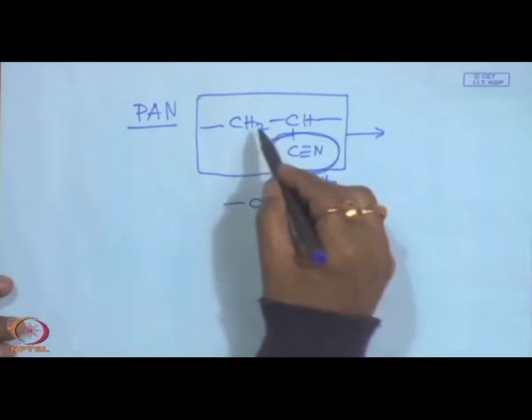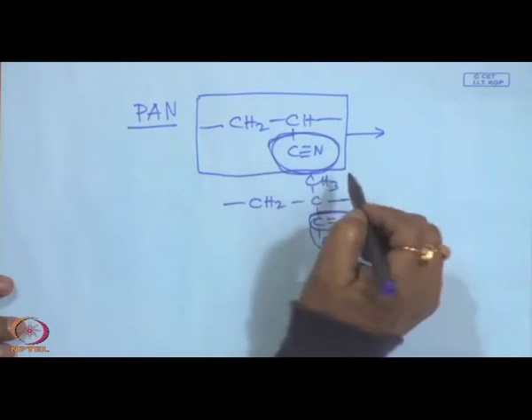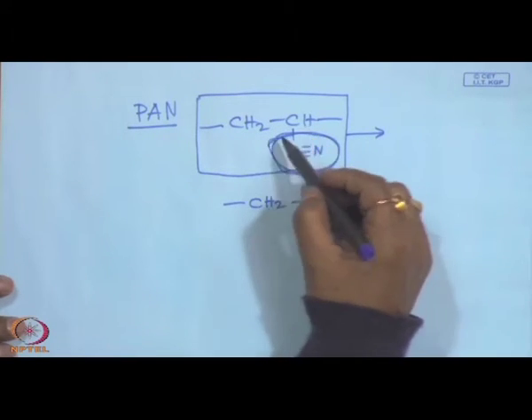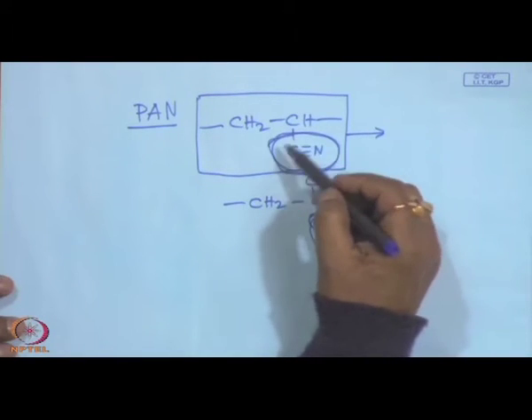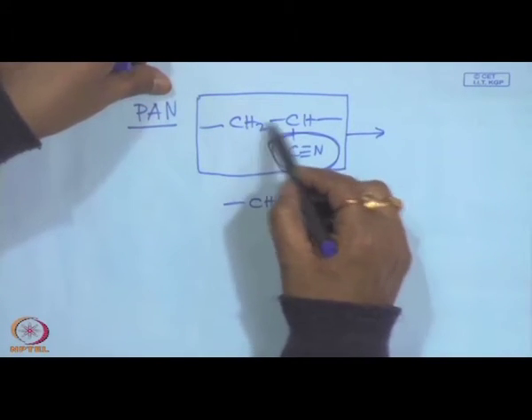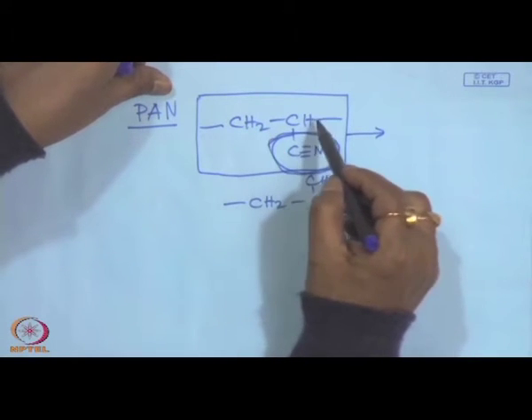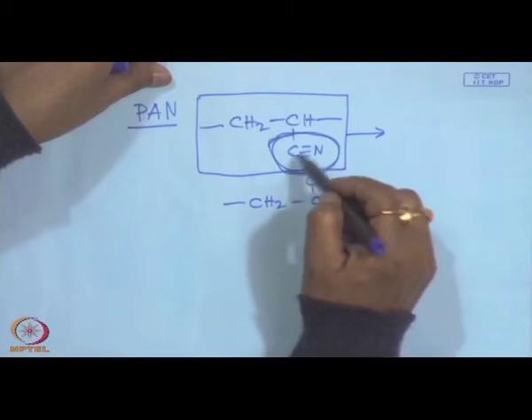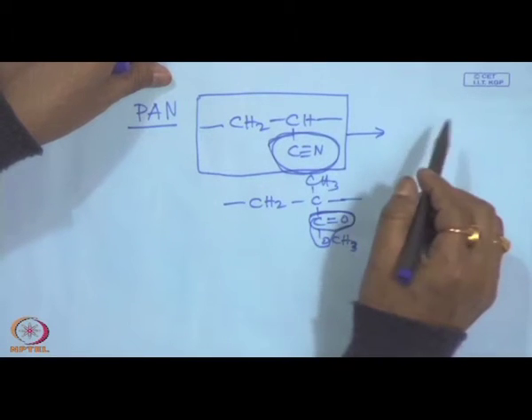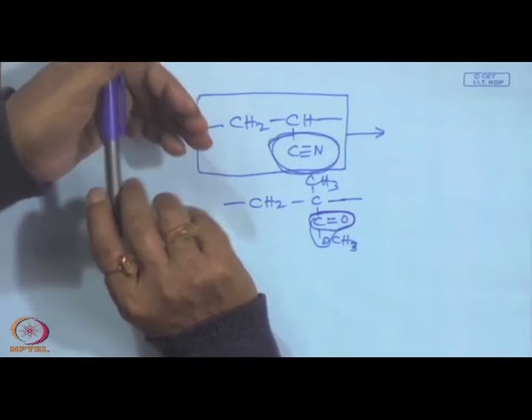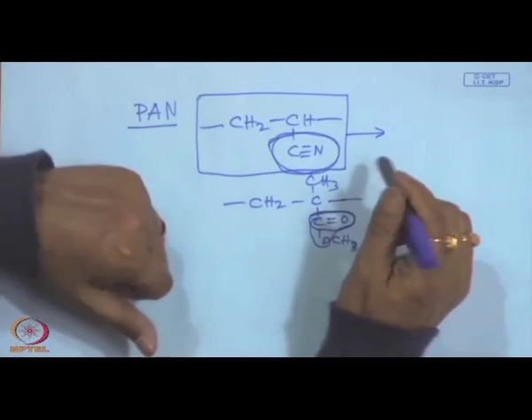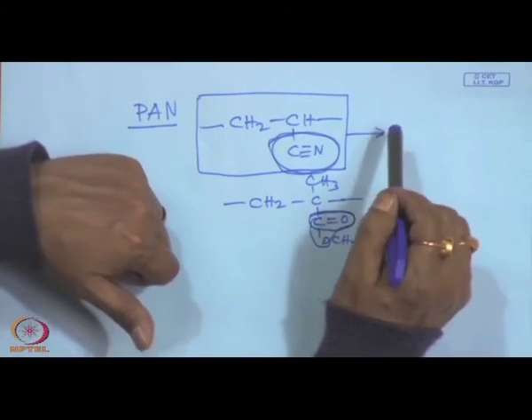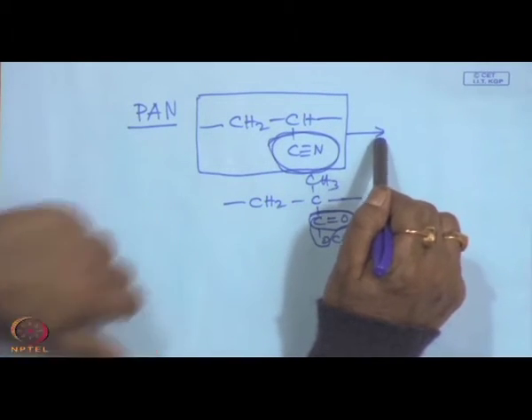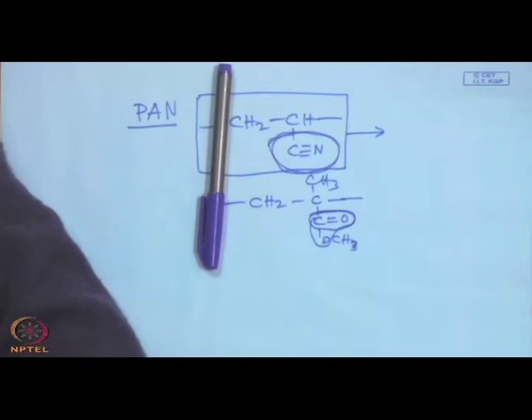This CN group cyclizes with the adjacent nitrile linkage. After cyclization, gradually when it is heated in inert atmosphere, it cyclizes and these hydrogens are expelled out, and then it forms a hexagonal graphitic structure. So, that becomes stable as well as strong. So, that carbon fiber is used for making high performance composites, which can stand very high temperature as well as being very strong.